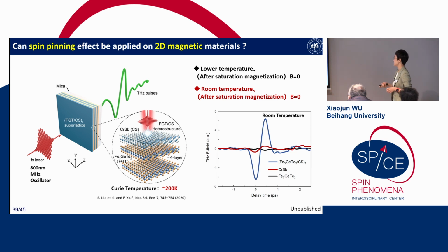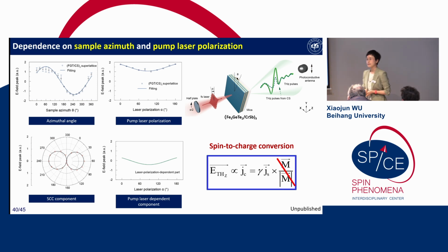What we observed here, the interesting thing, is that we observed terahertz radiation at room temperature, and there is a very small signal from the chromium antimony. So why can we observe terahertz at room temperature from this superlattice without external magnetism? To further find this mechanism, the routine work we do is to change the sample azimuth angle, change the pump laser polarization, and try to extract the SCC component. We can verify that this terahertz radiation mechanism is definitely spin-to-charge conversion.